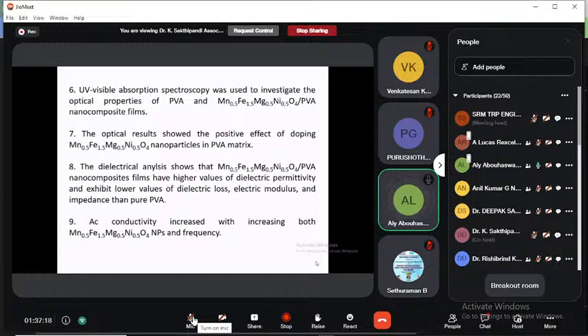UV visible absorption spectroscopy was used to investigate the optical properties of PVA and nanofiller nanocomposite films. The optical results show the positive effect of doping nanofiller in the PVA matrix. The dielectric analysis shows that nanofiller with PVA has a higher value of dielectric permittivity and exhibited lower values of dielectric loss, electric modulus, and impedance than pure PVA. AC conductivity increases with increasing both nanofiller and frequency.